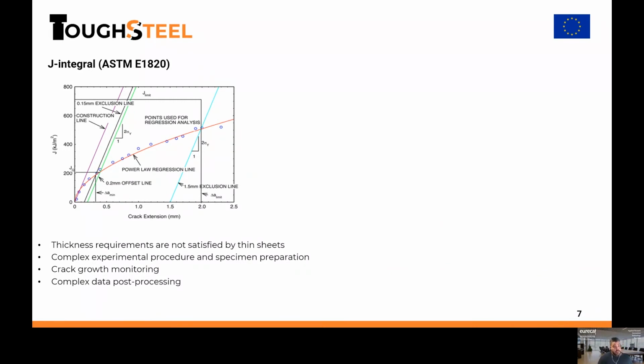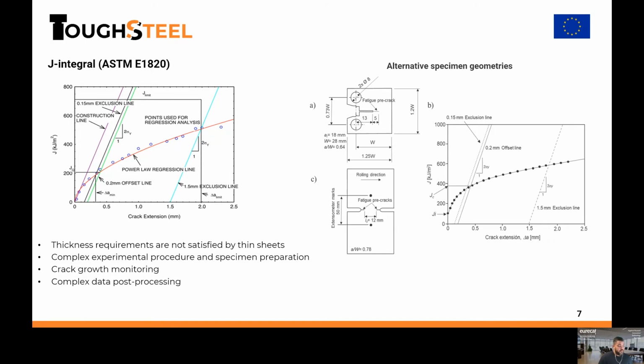The specimen geometries described in this standard procedure cannot really be applied to thin sheets, because usually the specimen geometries are based on a proportion with respect to the thickness. We're talking about 2 to 4 times the thickness, and since we are talking about thicknesses of 1 or 1.5 millimeters, the specimen size is not practical for testing. But if you use alternative specimen geometries, not taking into consideration the recommendations provided in the standard, you can also evaluate these J-resistance curves.